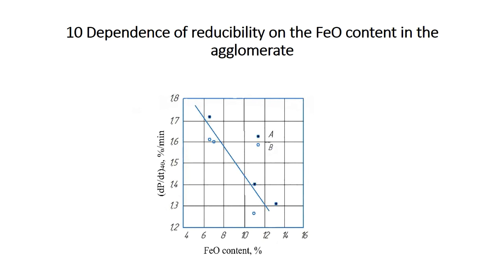But since with an increase in particle size, the need for coke increases, and thereby the FeO content in the finished agglomerate, Fig. 10 shows the dependence of the reducibility on the FeO content. With an increase in the FeO content in the agglomerate, the reducibility decreases. It is also seen that the reducibility of agglomerates from magnetite and hematite ore mixtures is the same.